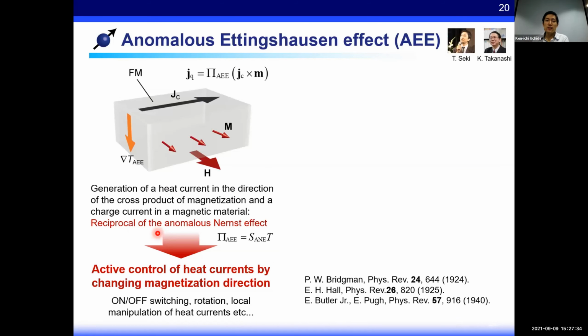The anomalous Ettingshausen effect refers to the generation of a heat current in the cross-product direction of magnetization and the charge current in magnetic materials. This symmetry means that the direction and magnitude of the heat current can be actively controlled by changing the magnetization direction. This phenomenon has also been known for a long time; its observation was reported nearly 1 century ago using bulk ferromagnetic materials.